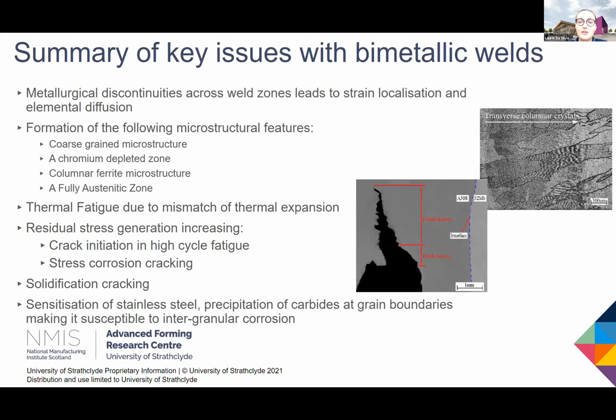A summary of the key issues that we can have with these types of bimetallic welds arise from the metallurgical discontinuities across the weld zones, and that leads to strain localization and elemental diffusion, and it can give rise to certain unwanted microstructural features. So you can have things like a coarse grain microstructure, you can have a chromium depleted zone from diffusion across a fusion line. You can also have columnar grains due to the direction of heat flow, but also you can have columnar ferrite grains because of carbon depletion from the heat affected zone from carbon migration through to the fusion line. You can also have a fully austenitic zone, and that arises when you have 2 things happening at the same time. So if you have a high carbon content and you also have chromium depletion in the same area.